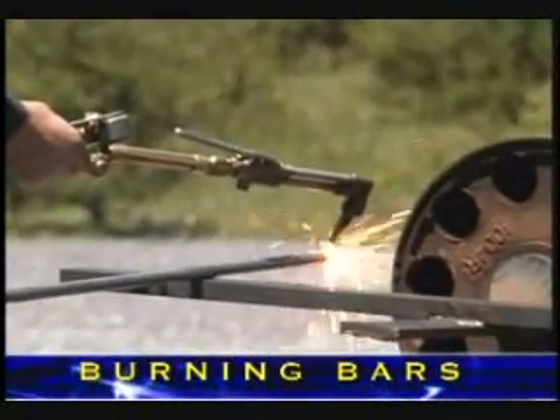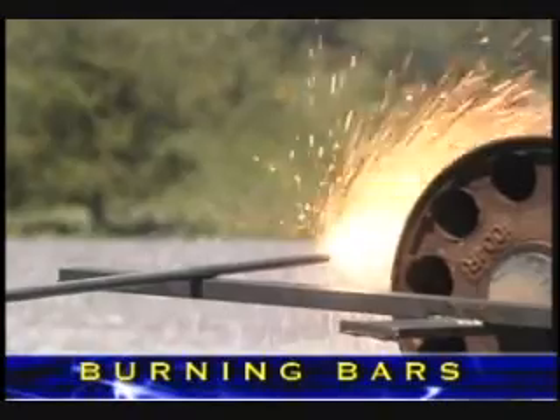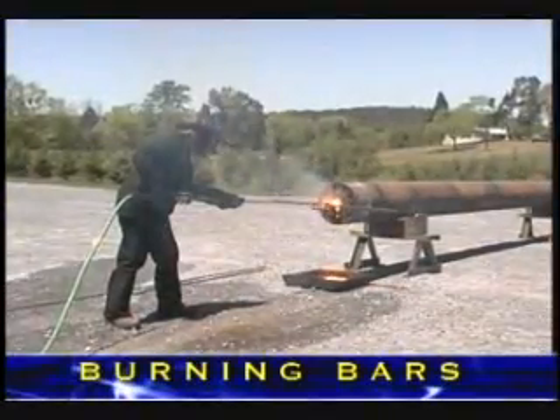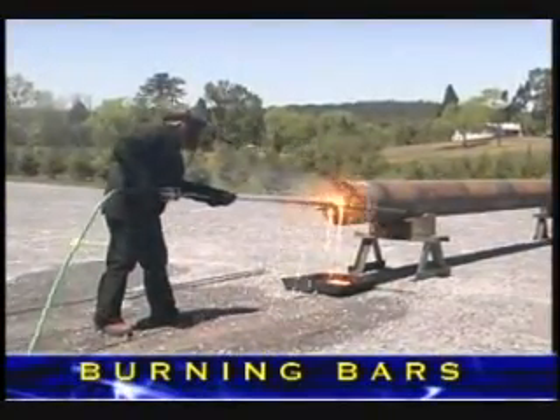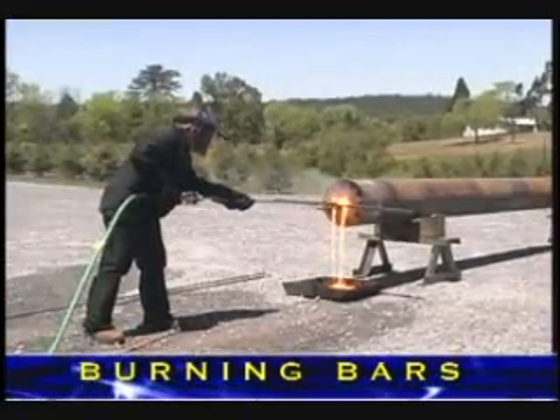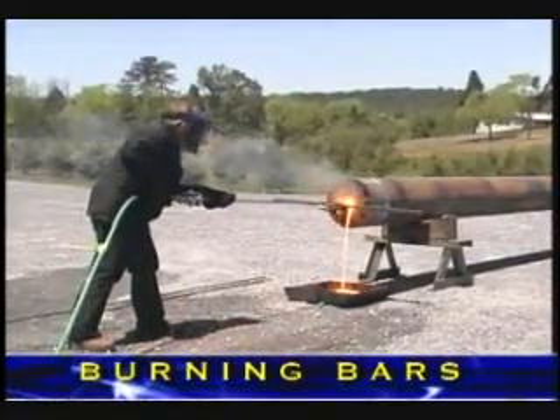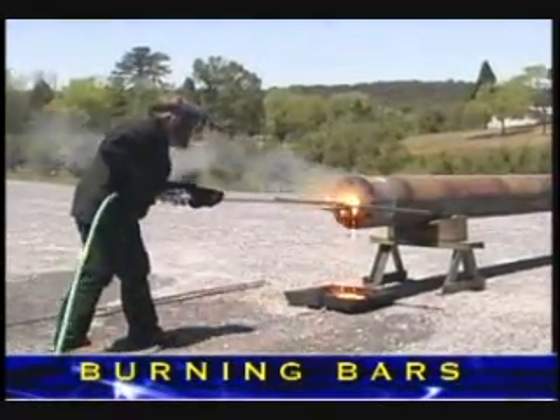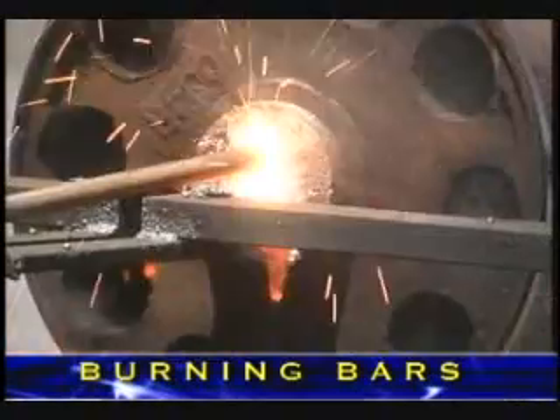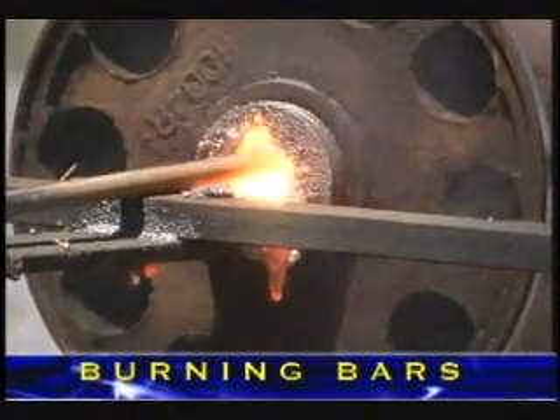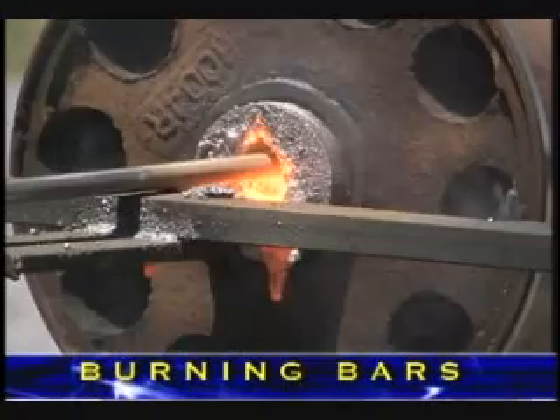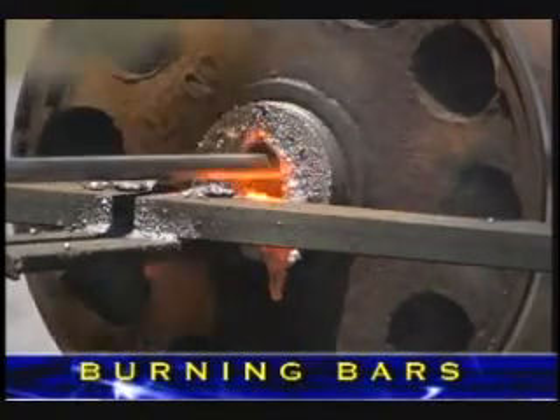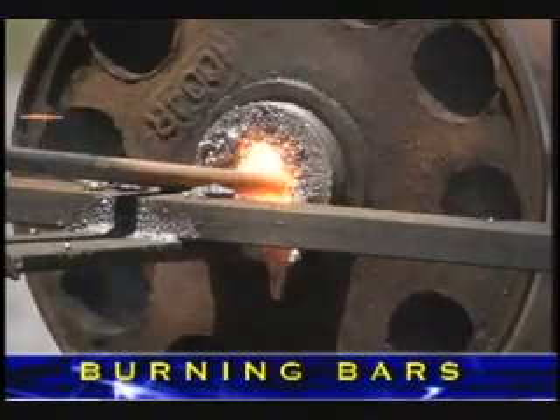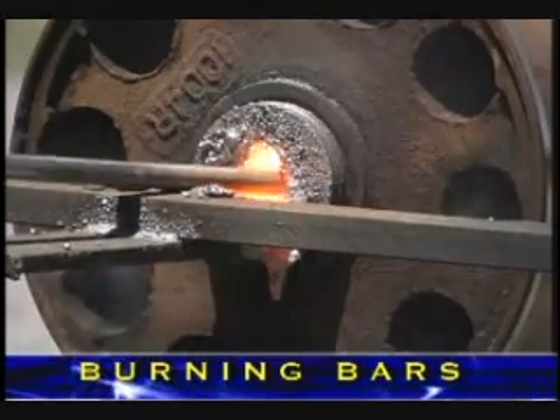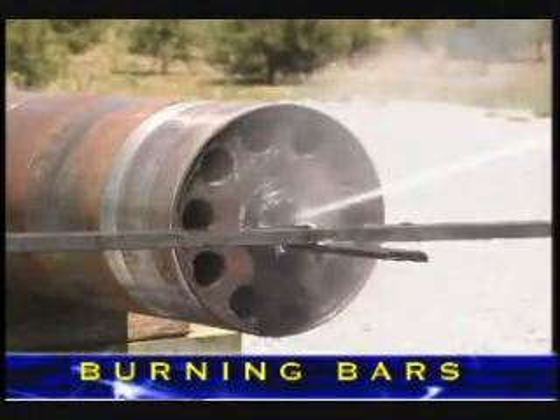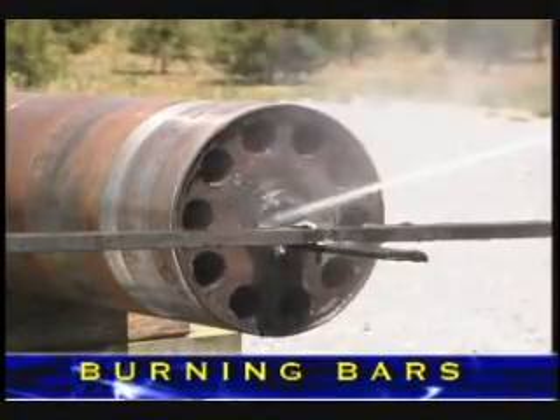Frozen pins can be removed from paper mill rolls or heavy equipment by piercing a hole through the center of the pin. In this case, the pin is 5 inches in diameter and 16 inches long. The time required for the initial pierce through the center of the pin was less than 1 minute. Enlarging the diameter of the hole 3 inches required an additional 3 minutes. By enlarging the hole, you give the pin more room to shrink when it cools. Cooling the pin took 5 to 7 minutes, and the pin was removed by hand.